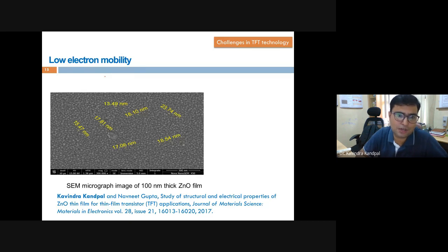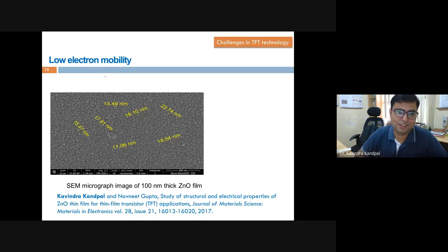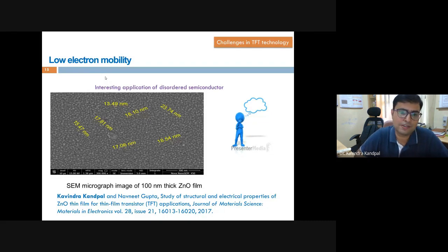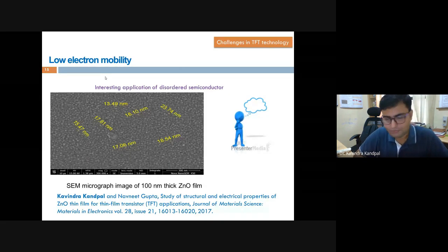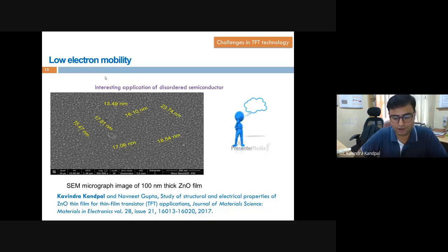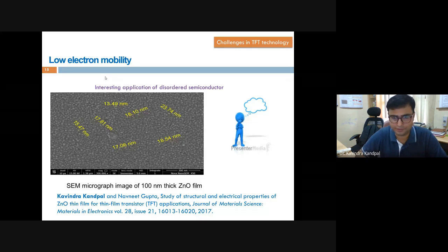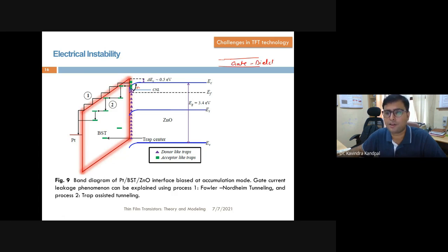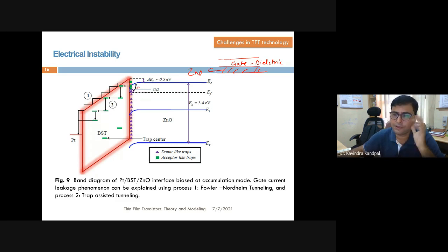Electrical instability is another challenge. The major contributor is the interface between the gate dielectric and the channel. If the interface is not defect-free, there will be many traps — energy-dependent traps that can cause threshold voltage instability. The applied gate voltage field lines may terminate at interface defects rather than modulating the channel, so the device may not behave as expected. The interface is therefore very critical in thin film transistors.